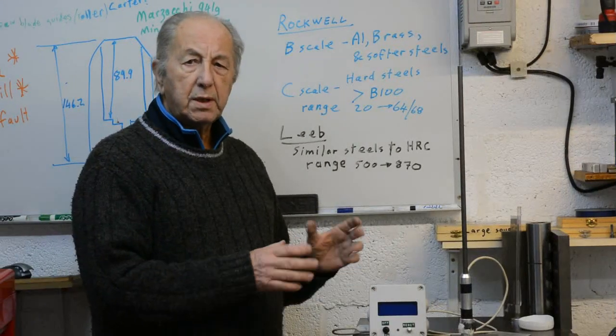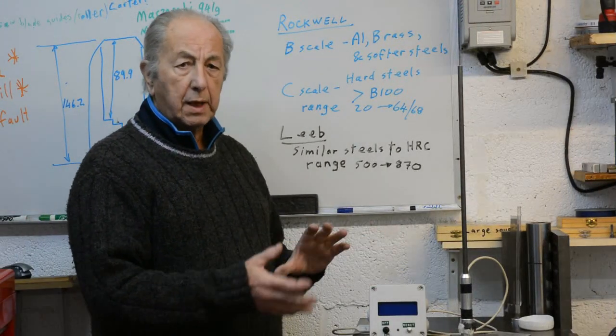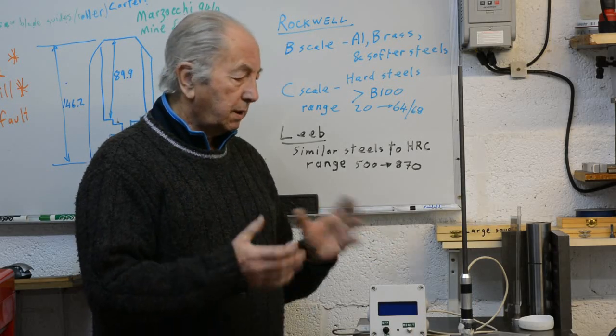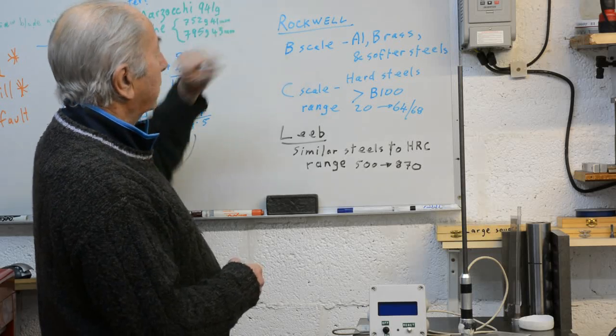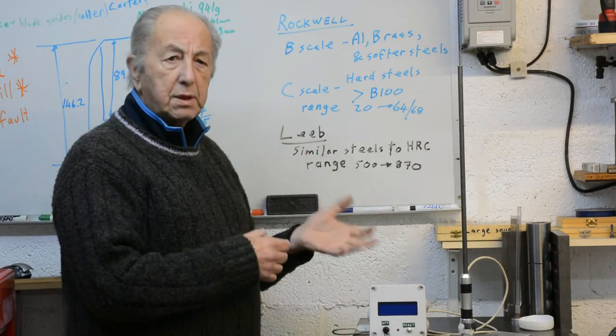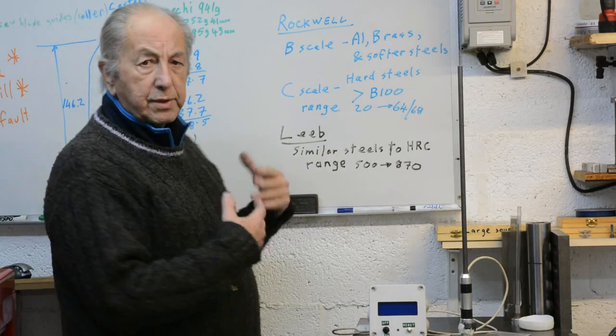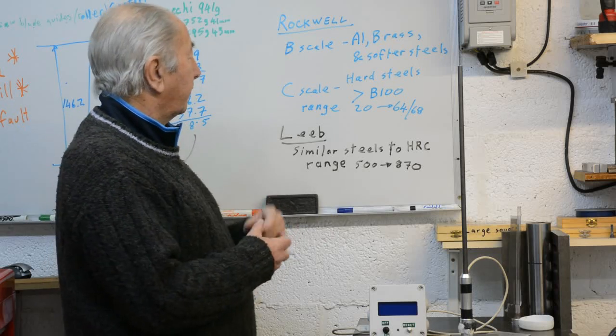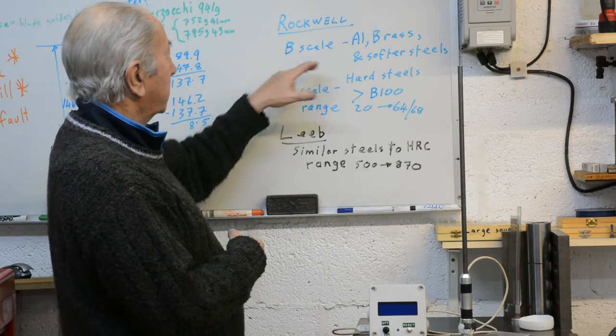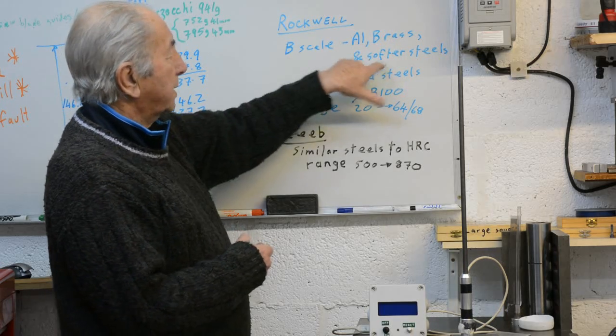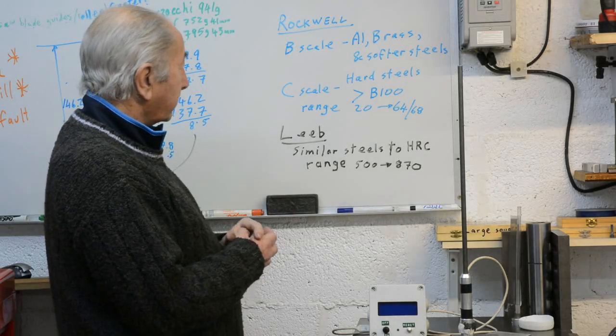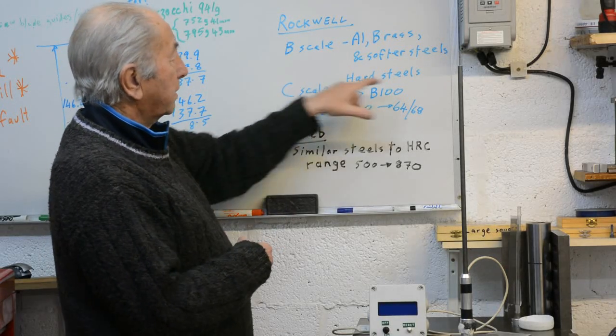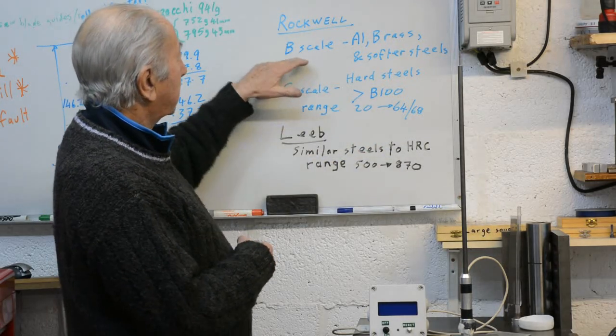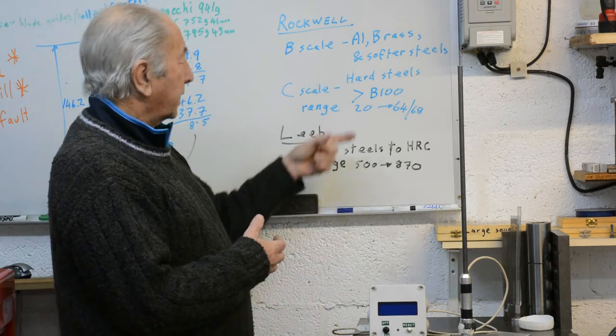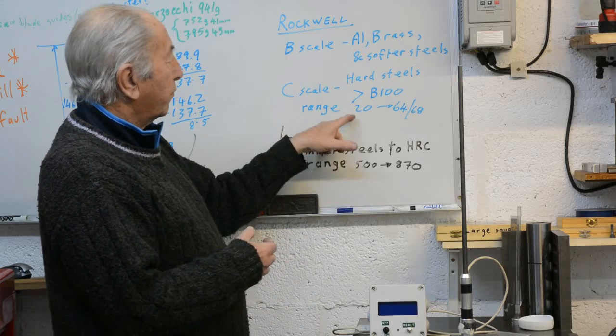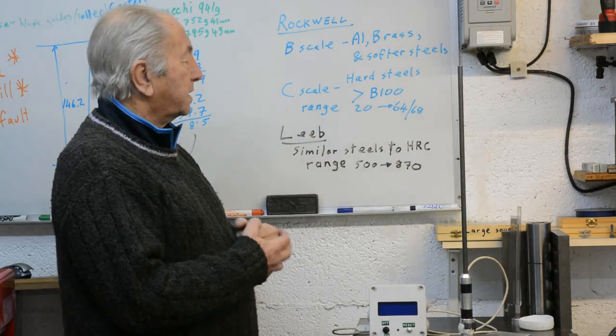Well, before we finish up, we need to talk a little bit about hardness scales and the dangers of how we use the numbers. First of all, just looking at the Rockwell, the huge range of scales for different materials and different special purposes. For our purposes, normally with metals in the workshop, there's probably the B scale and C scale, which are the most used. The B scale is for aluminium, brass and softer steels, etc. And the C scale is for harder steels. Steels that are harder than 100 on the B scale. The actual numbers of the C scale range from about 20 up to 64, 68.